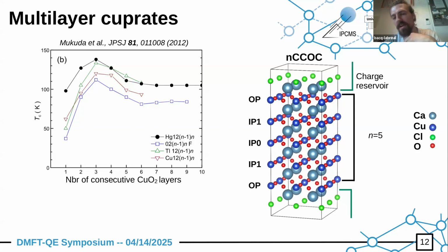Right now it's too expensive to do a cluster across planes. Yes, I understand that. We don't think it would be so sizable, because your hopping terms between the planes would be quite small compared to the others, and in such a case the self-energy would usually make it worse, because it would promote hoppings within the inner planes rather than between the planes. To describe superconductivity in very fine detail, perhaps you would need to include these interlayer correlations. But for the big picture, we don't think it's the main limitation, I would say.